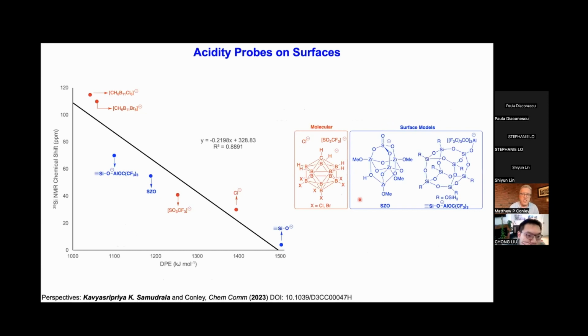If we use these small molecular clusters or use available deprotonation energies that have been given in the literature, we can see that they fall roughly on the same line as typical molecular anions that have deprotonation energies and known silicon NMR chemical shifts of their respective sililium or silane. So this is something that we're looking to build on to generate more weakly coordinating surfaces, to really get at these weakly coordinating environments that we can use regularly in the molecular community.